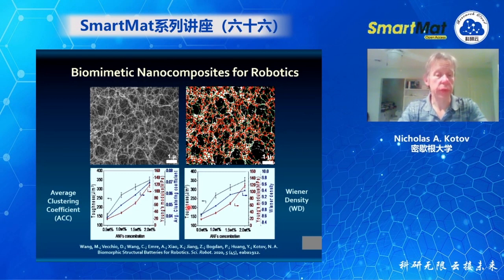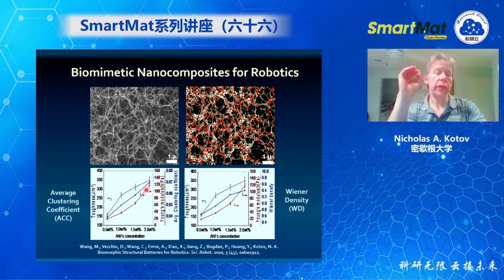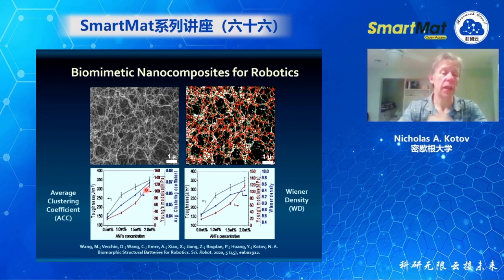But this required new types or new combination of properties, and by using the correlations of average clustering coefficients and Wiener density, one can see that now with organization of the nanofibers, we can actually choose this would be the average clustering coefficient, and that would be the Young's modulus and toughness. Interestingly enough, the ionic conductivity does not depend very much, so it's almost flat with respect to ACC. So that enables us to vary these parameters and retain another one.